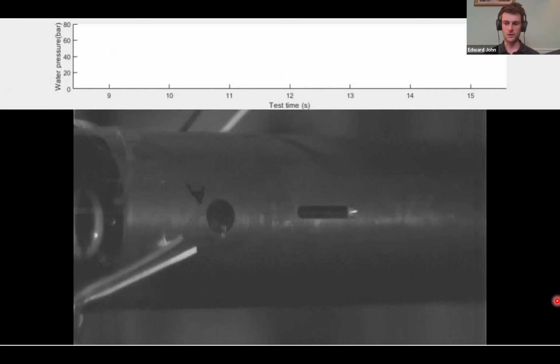So moving on now to look at some results from these tests. One of the things we did was use high-speed video recordings to capture the failure process to see what happened. This test shows one of the axial pits, and the only loading is internal water pressure. If you notice the pressure scale on the top, the pressure is quite a lot higher than we see in reality.